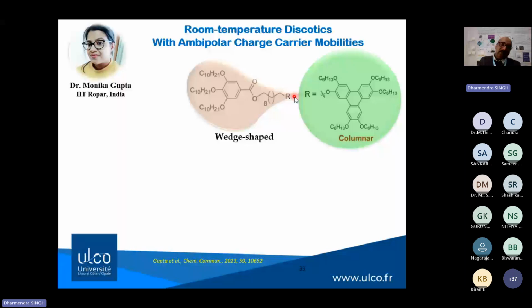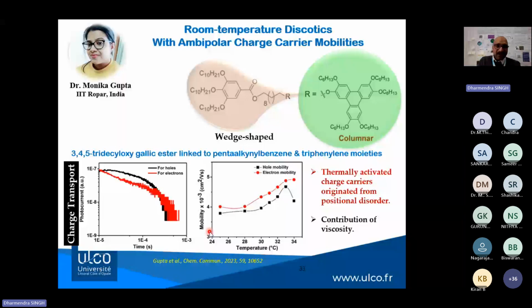When centrosymmetry is broken, you could see the mobility behavior here. We observed very nice photocurrent curves, and the mobility was on the order of 10 to the power minus 3. However, we observed temperature-dependent mobility. This was another proof of concept of the hypothesis from our last investigation, which was proven for this compound, and later on we communicated this in Chemical Communications. This charge transport phenomenon was driven by thermally activated charge carriers. These thermally activated charge carriers originated from positional disorder, because, as I told you, these are disordered systems. They are not ordered systems like crystalline solids.